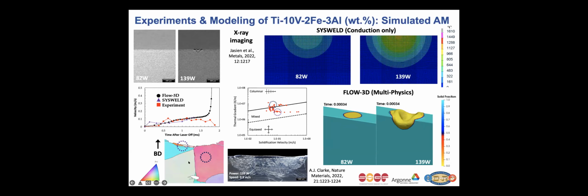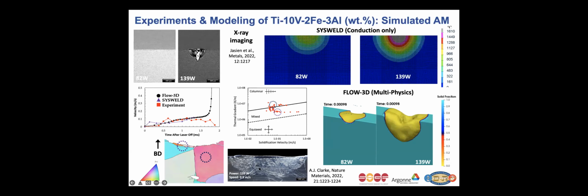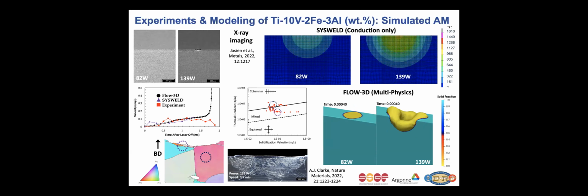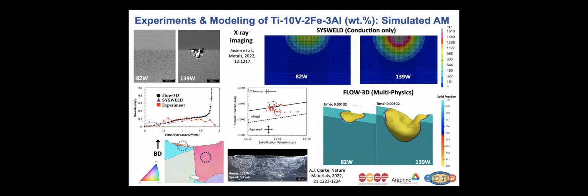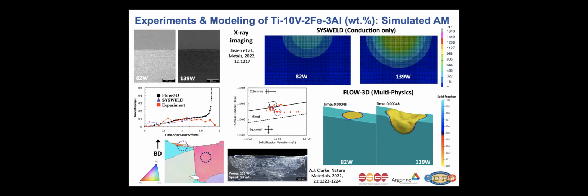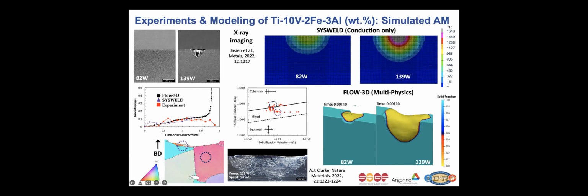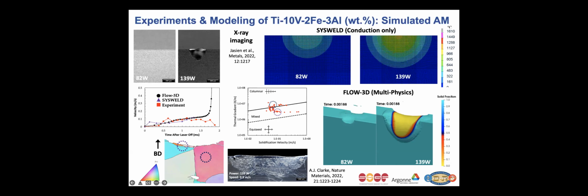One of the neat things about Ti-1023 is that if we have the retained metastable beta phase at room temperature, if we were to deform it, we have the potential to undergo transformation-induced plasticity, or TRIP, of the metastable phase to martensite with deformation. So here's an example of one of our laser track melts that we looked at at APS, and we can see this massive heat affected zone right below the laser track melt where we have martensite formation that occurs.